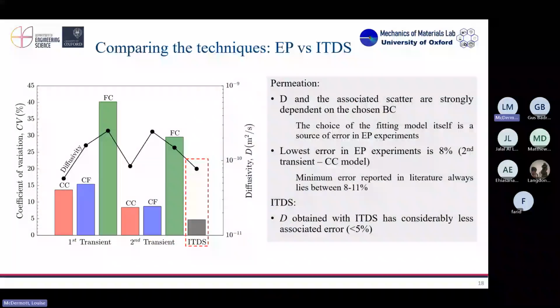So focus on this figure. On this figure, we have the methods that we used in the paper: permeation first transient, permeation second transient, and isothermal TDS, so the desorption method. The diffusivity is here, the black dots. You see variation of diffusivity depending on the boundary conditions that we use in permeation and in TDS. And this is the coefficient of variation of the more than 10 experiments that I performed using each technique.